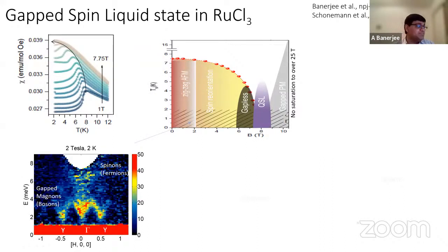How did we figure that out? We did neutron scattering measurements, and this is energy versus momentum. What we found out is that at low energies, low temperatures and low fields, you see this kind of an oscillating pattern of intensity. So red is high intensity, black is low intensity. This red region comes from elastic scattering, so let's forget about that. What we are more interested in is this cloud-like feature that we see here.